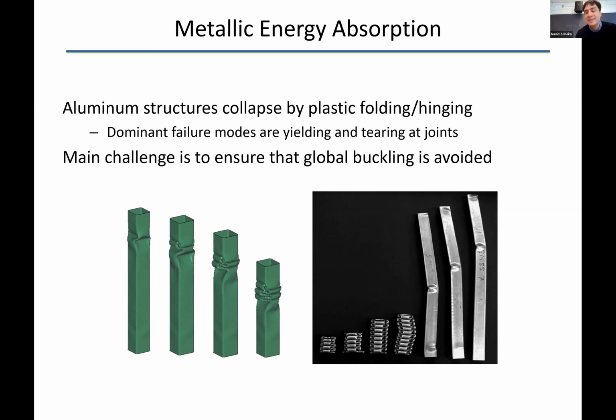Because basically, if you look at the stress strain curve, it basically goes through that yielding process, and the area below a stress strain curve becomes the amount of energy per volume that you're absorbing. So that's where you can take advantage of the material behavior. If it goes through yielding, better. Multiple of these you have, even better. So a case like this is the best case scenario that you might have for a metallic tube.